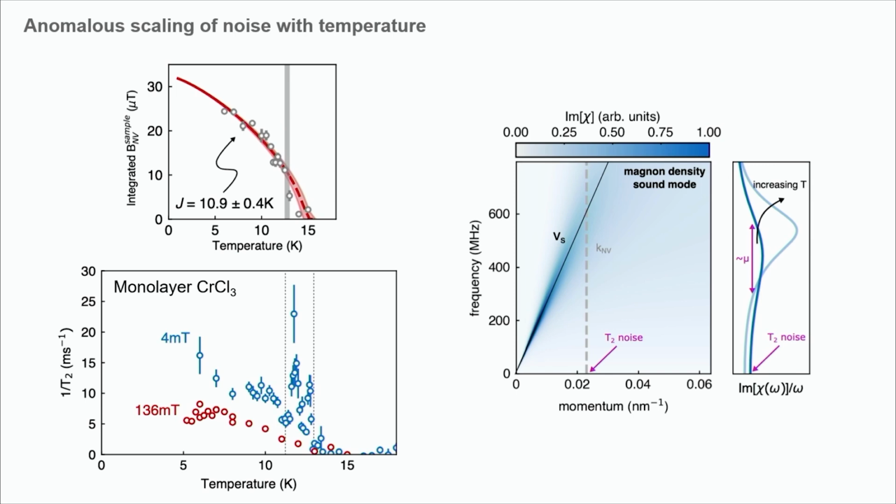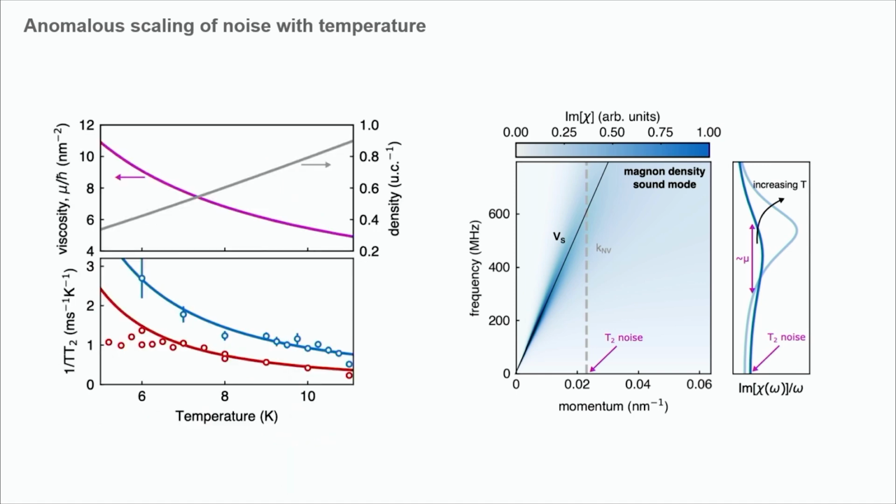So if I'm measuring fluctuations at this very low temperature, much of the spectral weight is getting shunted to higher and higher frequencies. That's the interpretation. We've done a more rigorous calculation and modeling of this trend, and qualitatively, it seems to capture the general behavior. What you're measuring is the viscous damping of this low-lying hydrodynamic mode, which increases as temperature goes down.